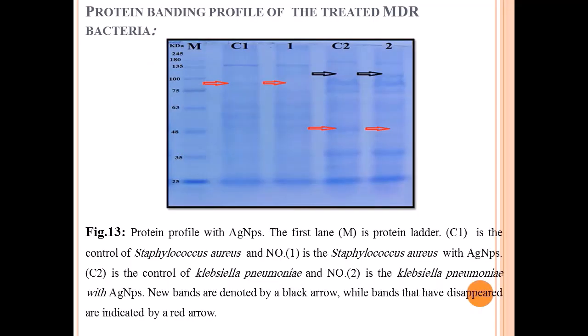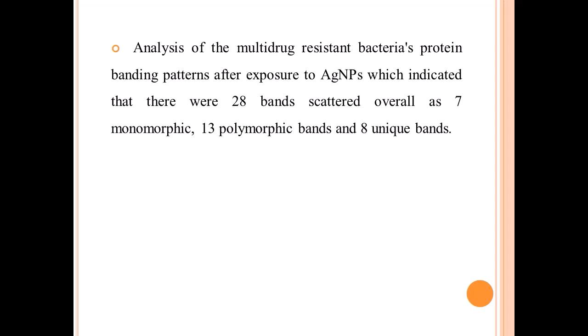Protein banding profile of the treated multidrug resistant bacteria. The first lane in the protein profile is the protein ladder. C1 is the control of Staphylococcus aureus and number 1 is the Staphylococcus aureus with silver nanoparticles. C2 is the control of Klebsiella and number 2 is the Klebsiella with silver nanoparticles. New bands are denoted by a black arrow, while bands that have disappeared are indicated by a red arrow. Analysis of the multidrug resistant bacteria's protein banding pattern after exposure to silver nanoparticles indicated there are 28 bands in total: 7 monomorphic, 13 polymorphic, and 8 unique bands.